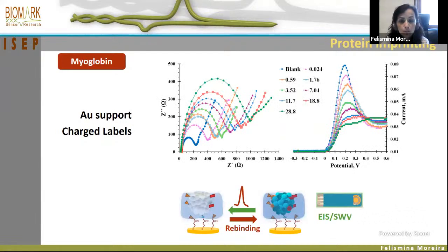So the analytical performance of the biosensor was evaluated by different electrochemical techniques. In this case, we used impedance and square wave voltammetry, and when we compare with the previous work that I present here, we achieved a lower limit of detection. We really were able to improve the operational features of the biosensor.